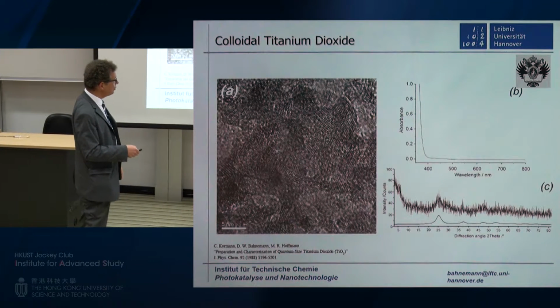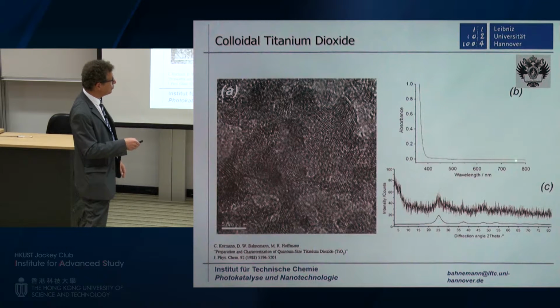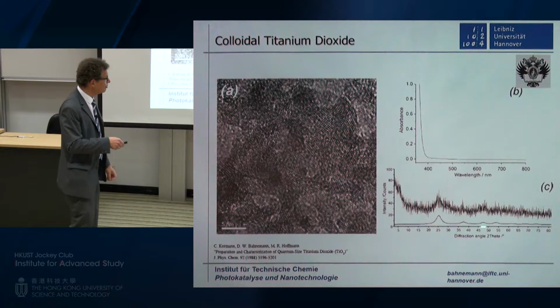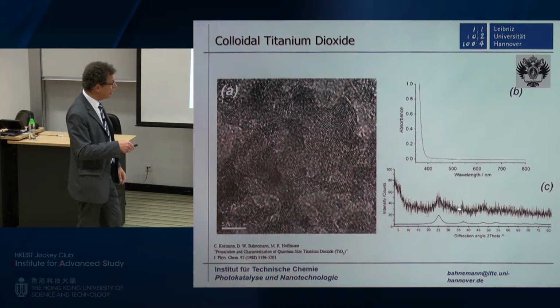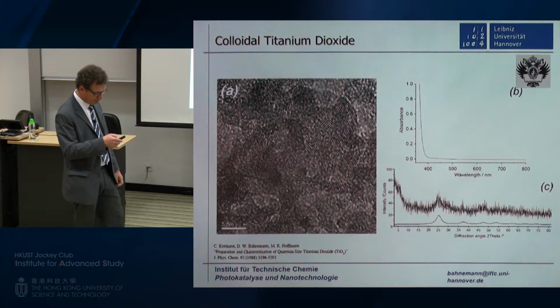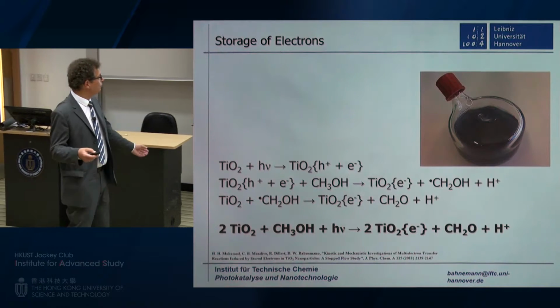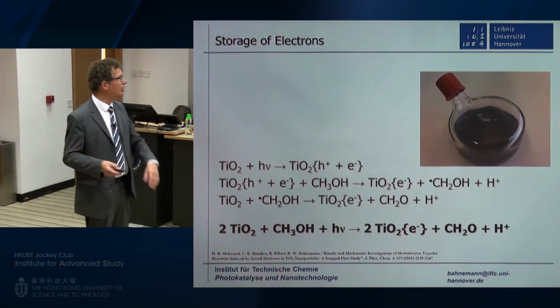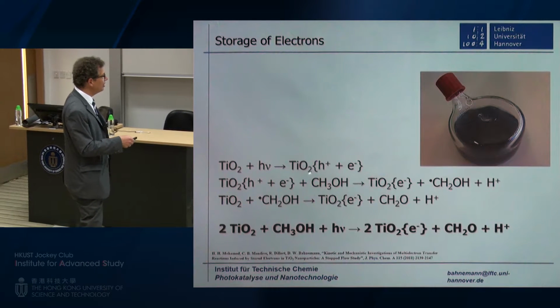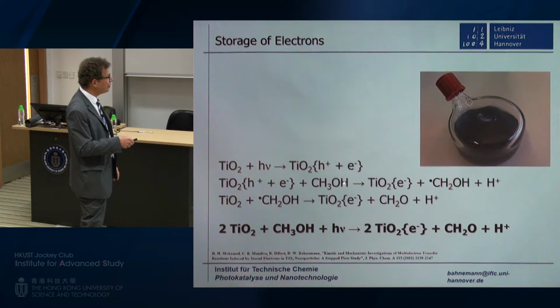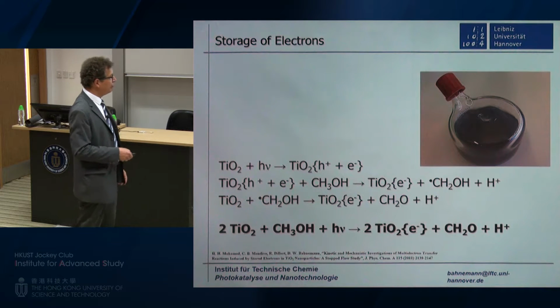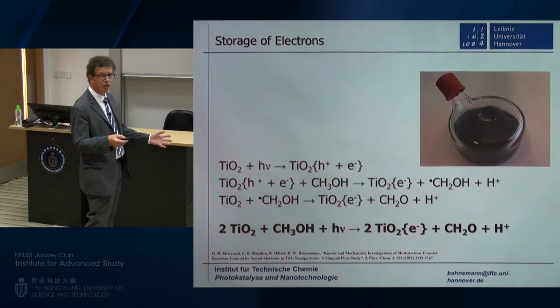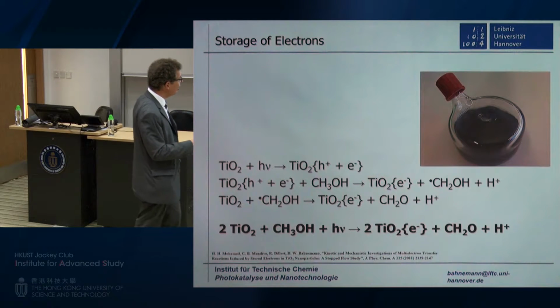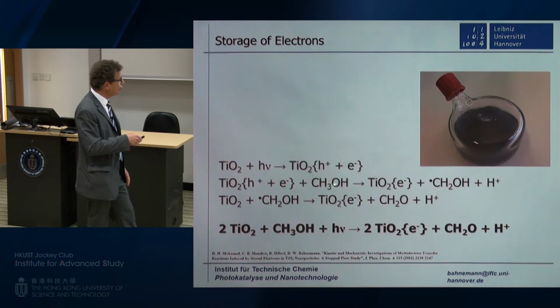Anyway, if you do this, you get nanoparticles which do not absorb any light in the visible and absorb only light below 400 nanometers. And if you look at their X-ray pattern, you see that they are already anatase nanoparticles. And now we did a very simple experiment. We took the system similar to the one I've showed you before. We just illuminated it in an aqueous suspension containing methanol. And if you have methanol in the system, you have exactly the same reaction like I described with the polyvinyl alcohol. Methanol is a very good electron donor.